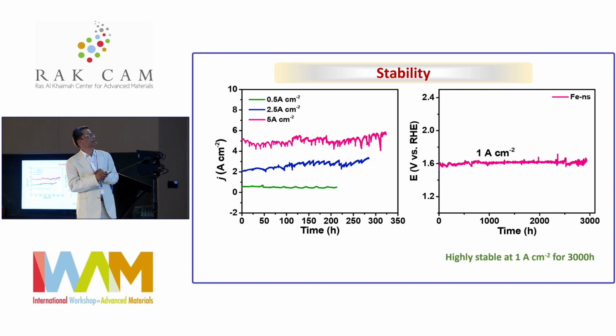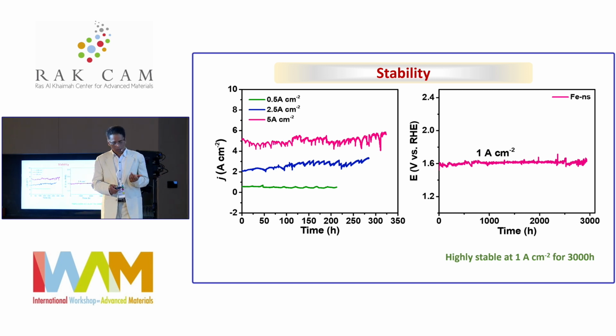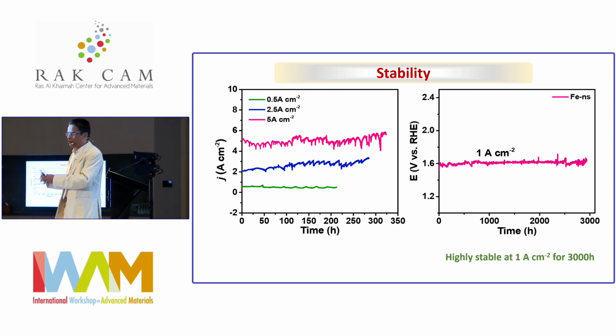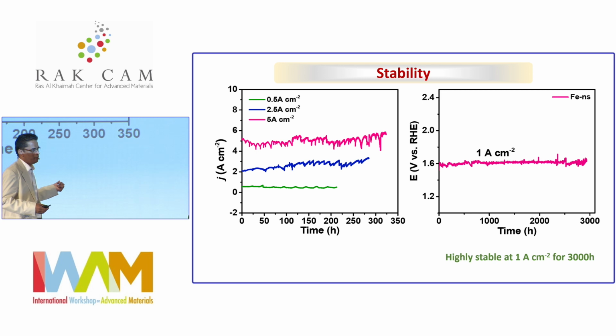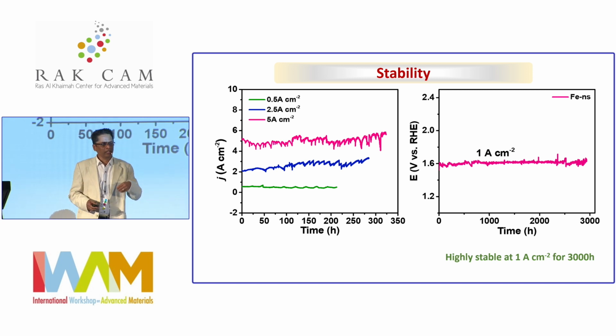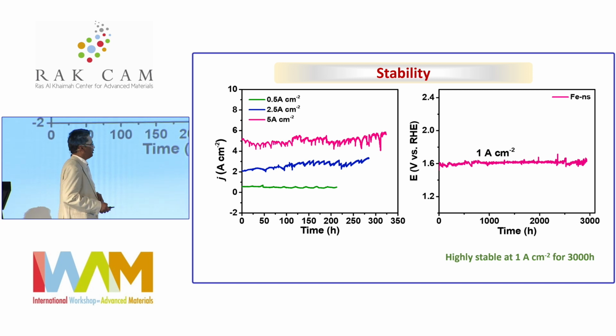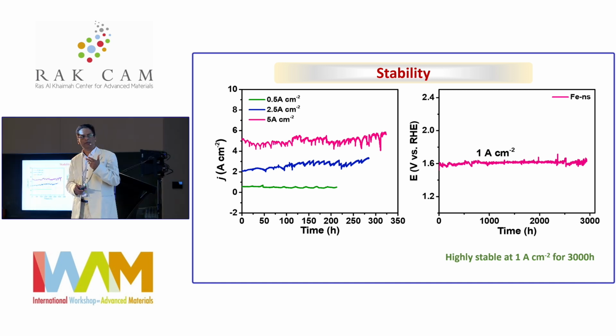Even at 5 ampere current density, it is stable for more than 300 hours. So we are now looking into it. In fact, when you do the reaction, scratch the material, put it on carbon paper and do the reaction again, the increase is there but we don't get that activity. The analysis of those materials shows the formation of a new phase of nickel and iron with a spinel type of structure, and it's still not clear whether that spinel or some other structure is the active one behind this.